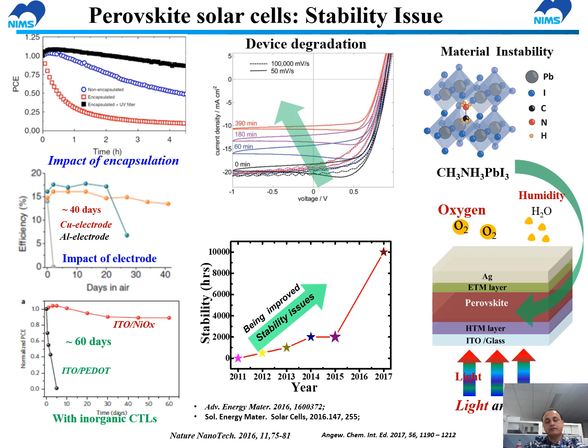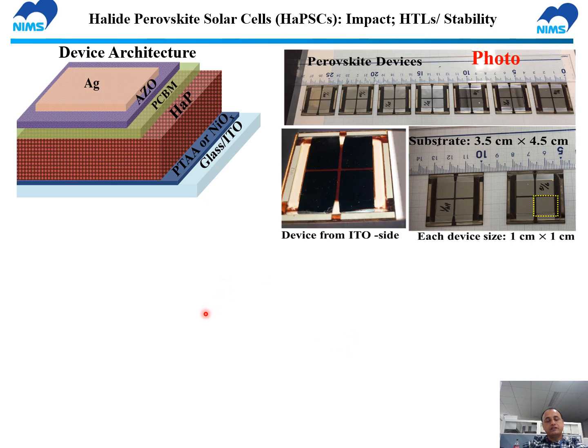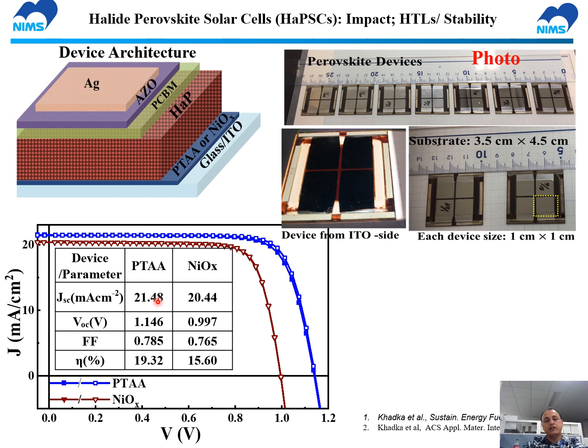However, the device degradation phenomena are still not completely known, and there is much room to understand the device degradation mechanism. To understand the device degradation kinetics, we prefer devices with PTAA and nickel oxide as hole transport layer. This is a device with device area 1 centimeter square, and this is the JV characteristic. We fabricated a device of more than 19% efficiency with PTAA, and the device with nickel oxide has efficiency close to 16%.